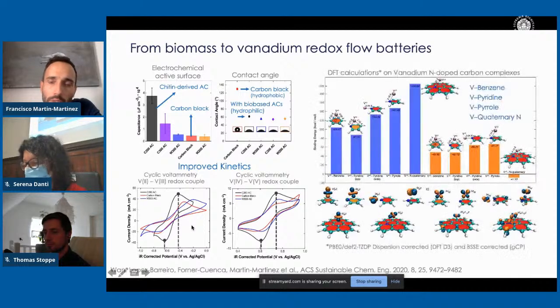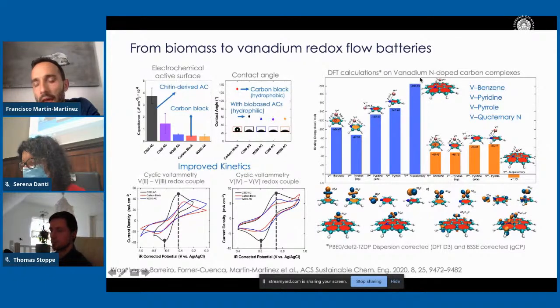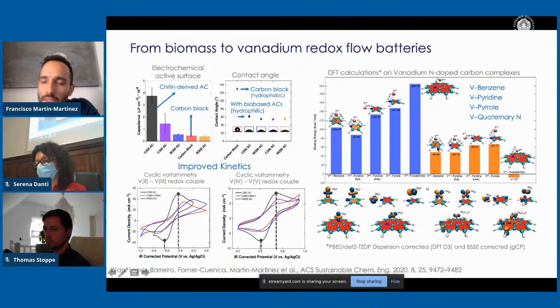Doing the modeling, what we saw is that indeed, you can compare whether for vanadium 3 or 2, you can see how all the species with nitrogen have a higher binding energy than those species in which it binds only to carbon. So nitrogen indeed improves the adsorption of that vanadium species, and that helps improve the kinetics.